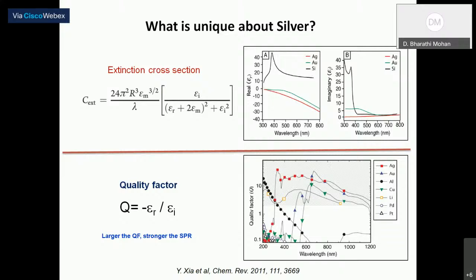If the resonance condition is to be satisfied for any plasmonic material, the extinction cross section must be very high. It is very high only when the real part of the dielectric function of the material is negative. If you look at the denominator of the bracketed function, the real part of the dielectric function should be the negative of twice the dielectric function of the medium. Only then the bracketed function approaches 0. When the bracketed function approaches 0, the extinction cross section becomes high.